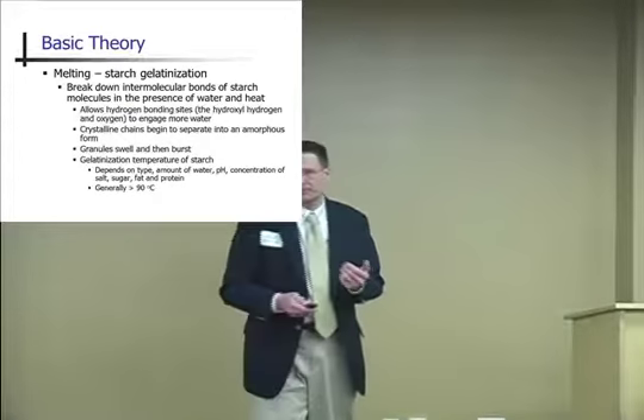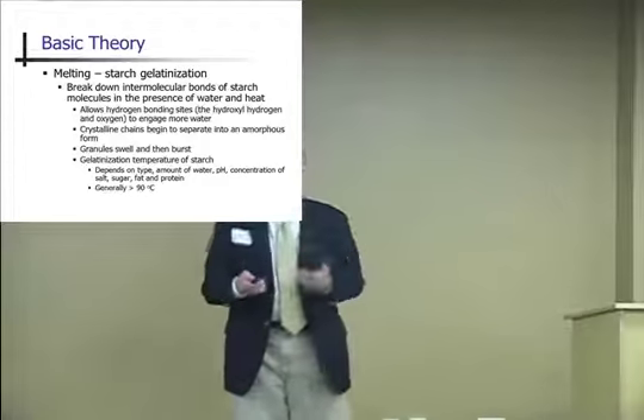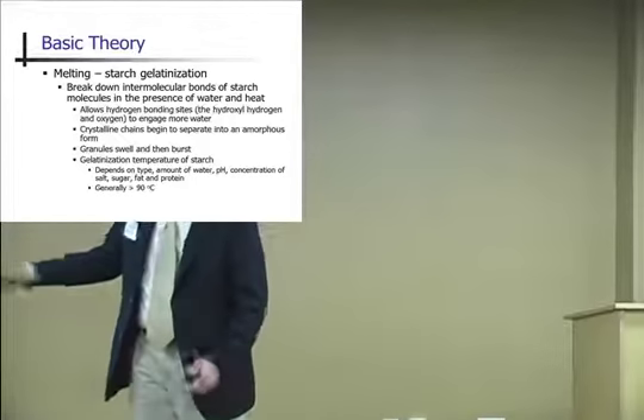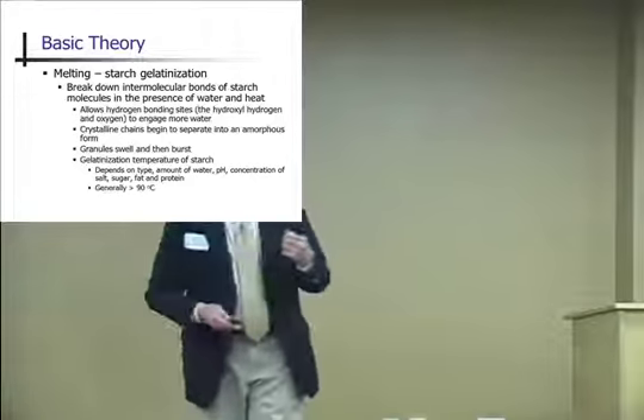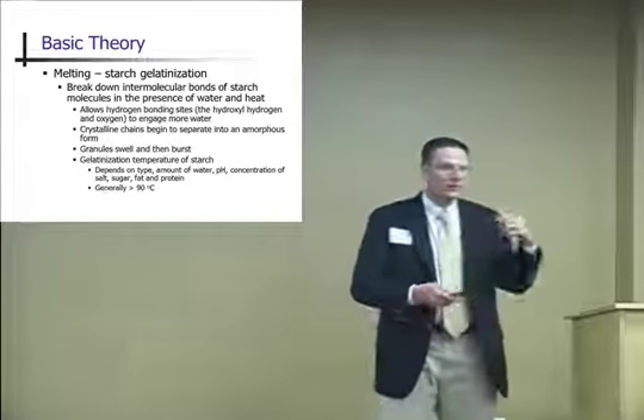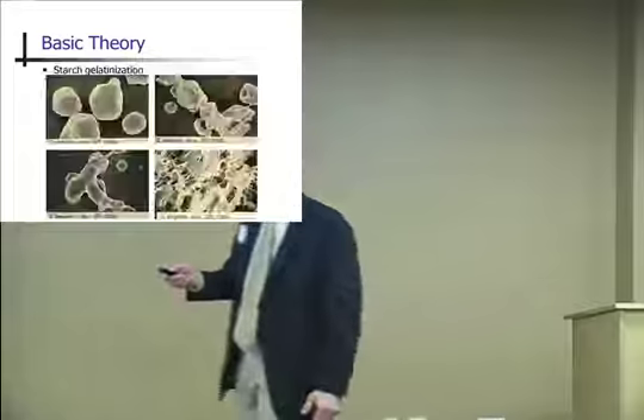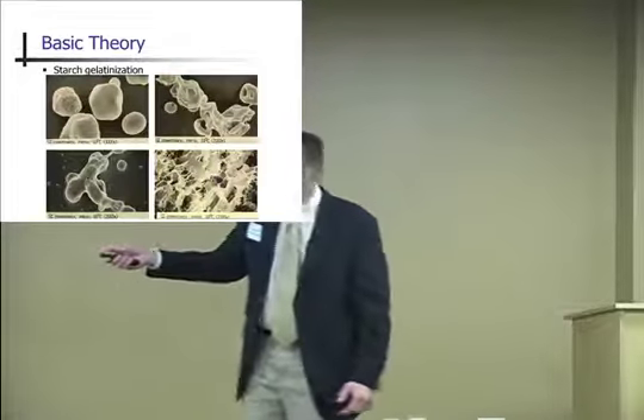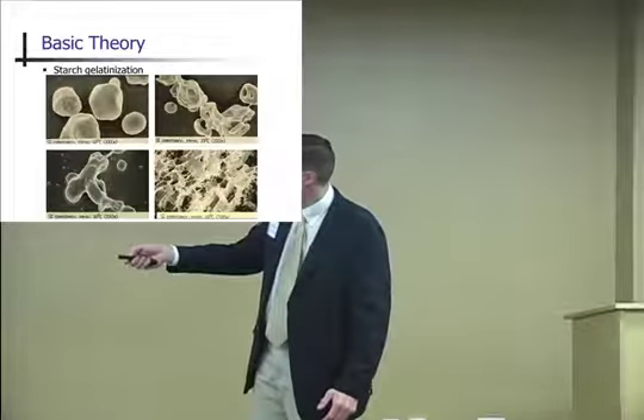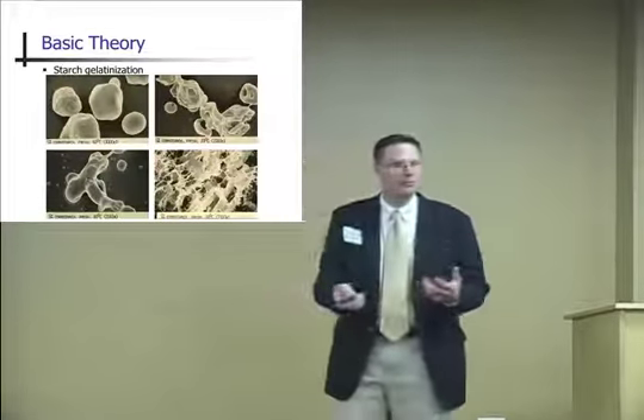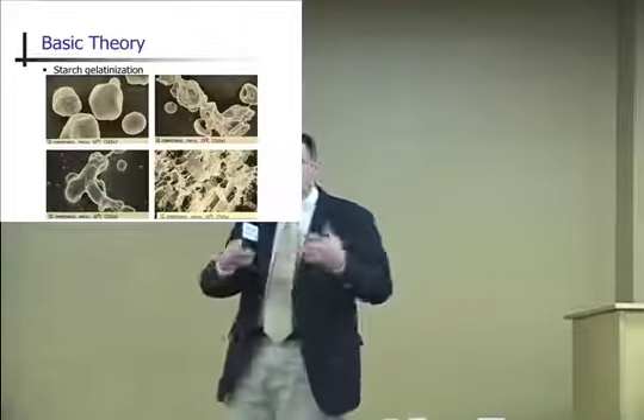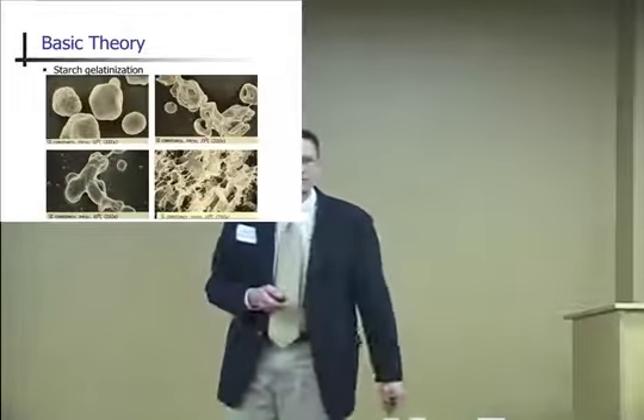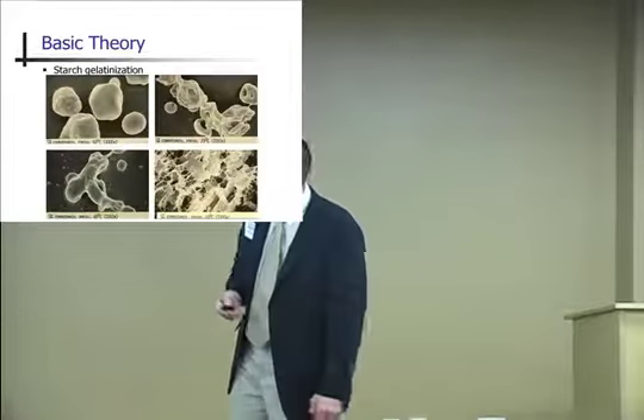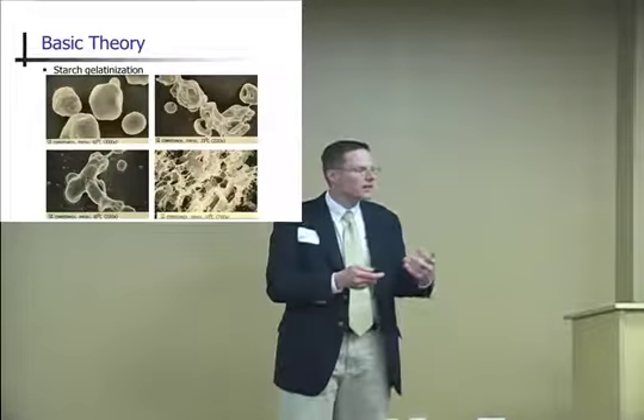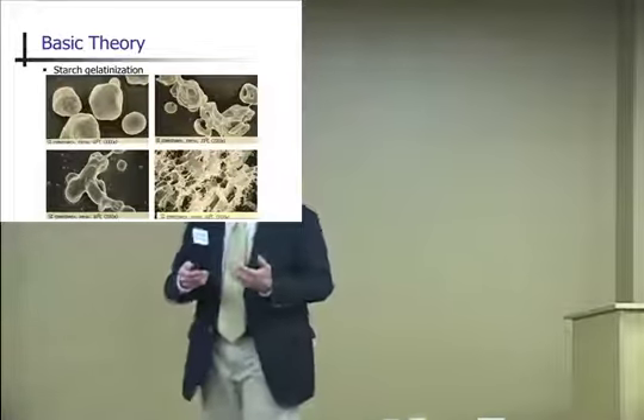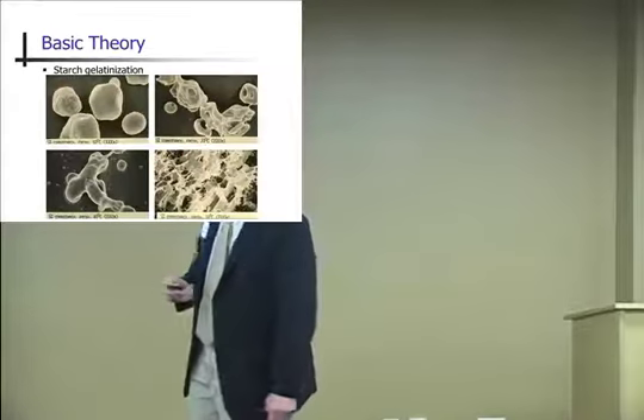So starch is key. Starch is the glue that holds the ingredients together as they exit out of that die. So as you're manufacturing feed, you want the starch to break down, because initially starch is globular in structure. So this is at 60 degrees. At 80 degrees, we see this network, this glue will surround all of the other particles and hold them together in a matrix. So we want the starch to melt. The glue, basically, allows water and other materials to bind to the starch molecules.